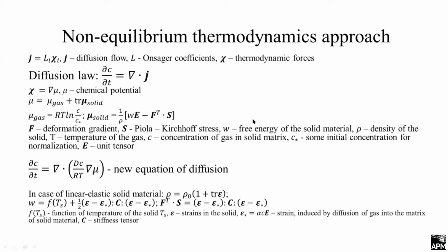So we use a non-equilibrium thermodynamic approach. We use the approach of Prigogine and Onsager, saying that diffusion flow depends on thermodynamic forces and Onsager coefficients. The thermodynamic force is a gradient of chemical potential, and as we are looking at gas diffusion and neglect everything that happens with the metal, we just need to take into account how the metal and its potential affect diffusion of the gas. So we use the well-known chemical potential of the gas and the chemical potential of the solid, which is the energy-momentum tensor, which is quite well known.